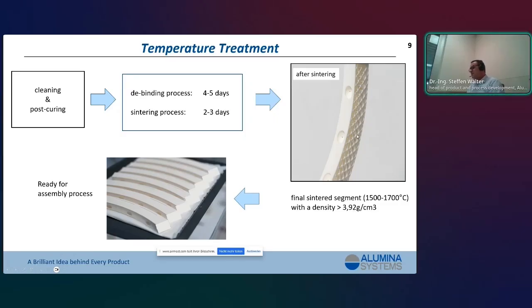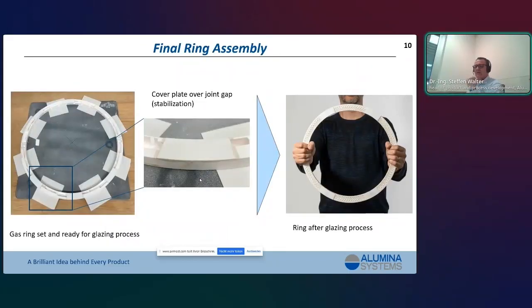Such parts will be sintered, for example, in a final sintering stage at between 1500 and 1700 degrees C to get really dense alumina segments. So if you have these segments, we are ready for the assembling process. So we have here a bunch of these segments, and now in the next pictures we bring these ring segments to a part, to a ring.